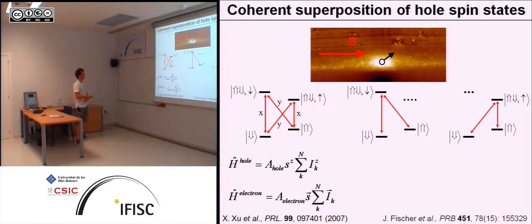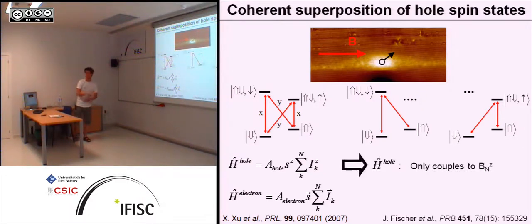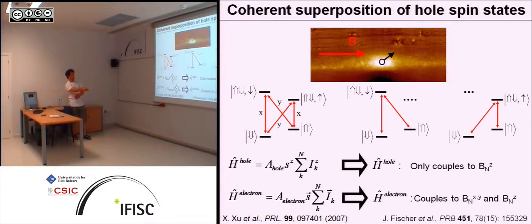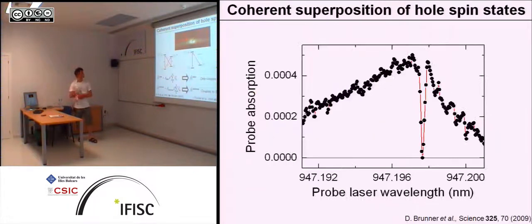The other interesting bit is if you look at the interaction Hamiltonian between nuclear spin and hole spin, or nuclear spin and electron spin, they actually have a very different asymmetry. So this is basically the sum of H1, H2, and H3, these different dipole coupling terms I introduced before. And it can be shown that for holes, this Hamiltonian has a very strong asymmetry in direction, while for electrons it doesn't. So this only couples the Z components of carrier spin and nuclear spin, while this here couples all components. So that means the hole only couples to the Z component of the nuclear magnetic field, while the electron couples to all of them. And that means that if you apply a magnetic field in X direction, at least for the holes, you can suppress the remaining interaction very, very strongly.